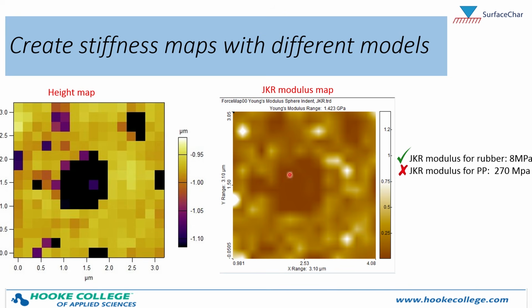And we can see that the rubber domains, not surprisingly, are showing a much lower modulus than the surrounding thermoplastic matrix. The thermoplastic in this sample is polypropylene. And so when we actually measure the moduli from this image, what we get is a modulus for the rubber of about 8 megapascals and a modulus for the polypropylene of about 270 megapascals. Now the modulus for the rubber coming in at around 8 is correct. The modulus for the polypropylene is incorrect by about a factor of 5.